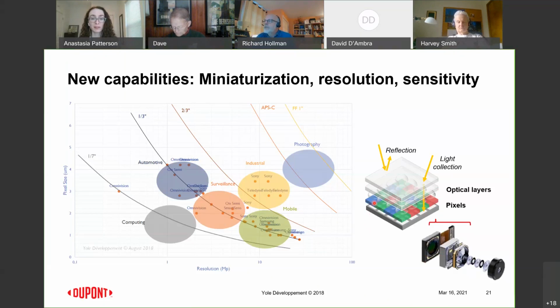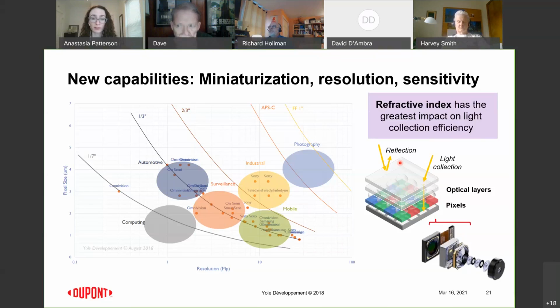And so because of that, very small percentage changes in the efficiency of light collection can make a really big difference in the sensitivity. And these optical layers are really what dictate how much light gets to the back of the camera. And you can see, there's lots of lenses placed way out here, but then in the back of the device, there's a lot of optical layers involved. And what dictates light collection versus light reflection, which is not what we want in terms of collecting photons, really is the refractive index of those films. And so that's what I'll be focusing on for the second portion, is controlling refractive index of these types of optical films to increase the efficiency of collection based on these reflection type interactions.